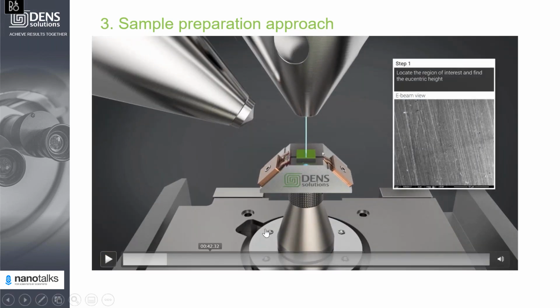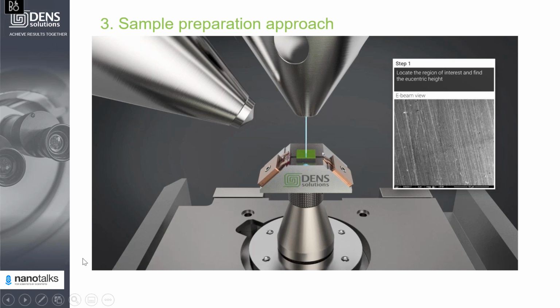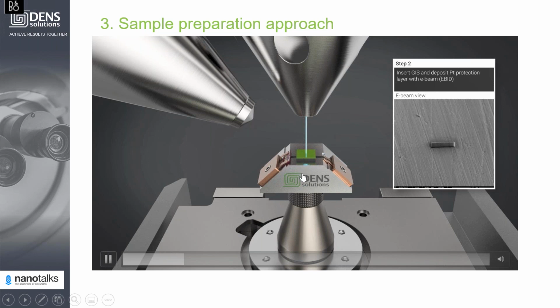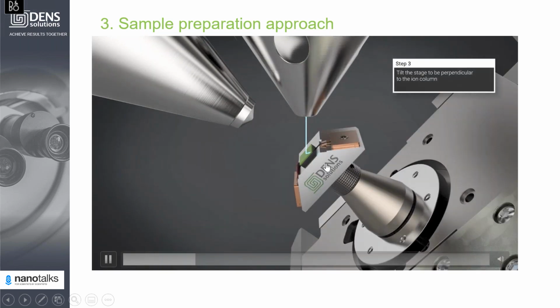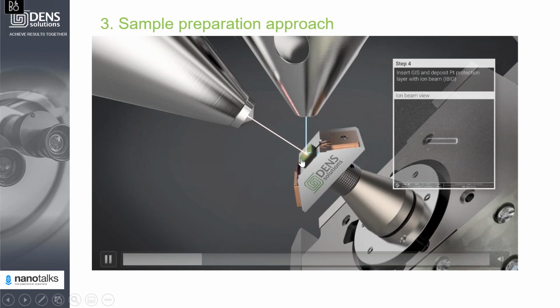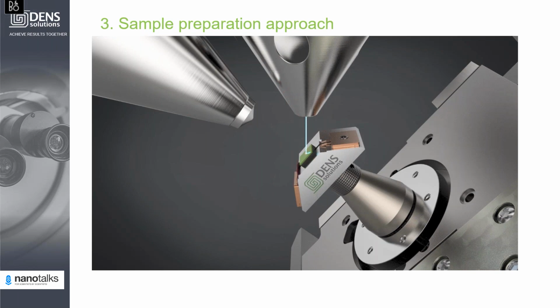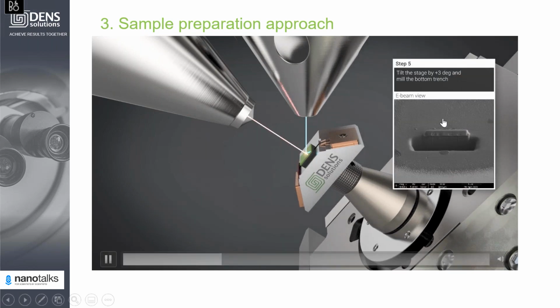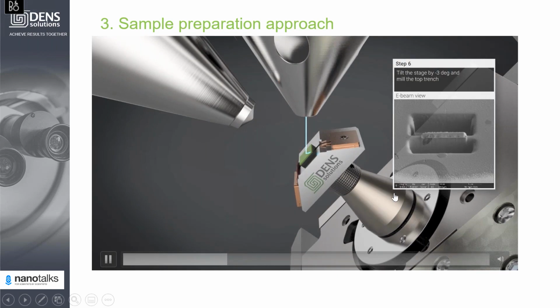So the first part is what I mentioned. Because of the flat geometry of the FIB stub, you can apply the well-known process. Basically, everything you know, you can just apply your knowledge here. First, you find the sample and set the working distance, the eucentric height. If you need, you put electron beam platinum. If not, you tilt the stage to be perpendicular to the ion beam and make the ion beam deposition of the protection layer, which is mostly platinum. Afterwards, you make trenches. You can do it either one by one, or you can do it together, with small tilts or without. It depends on your own preference.